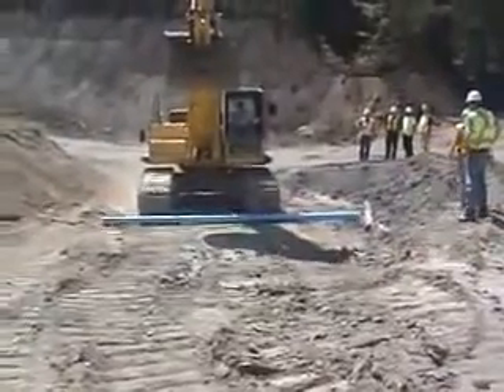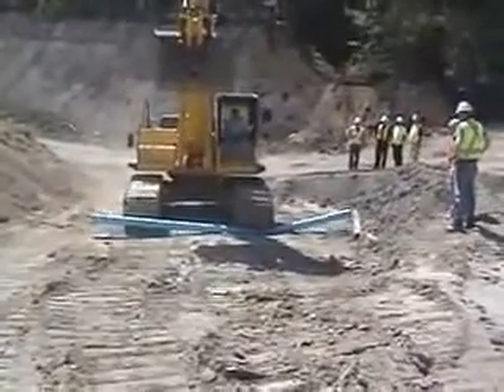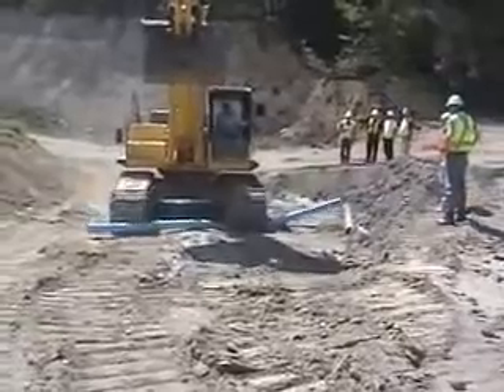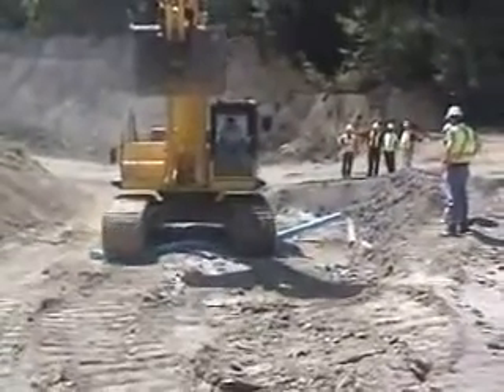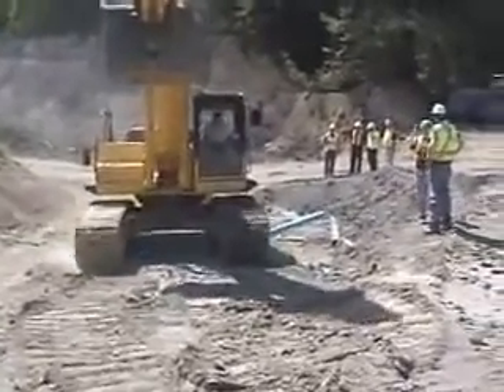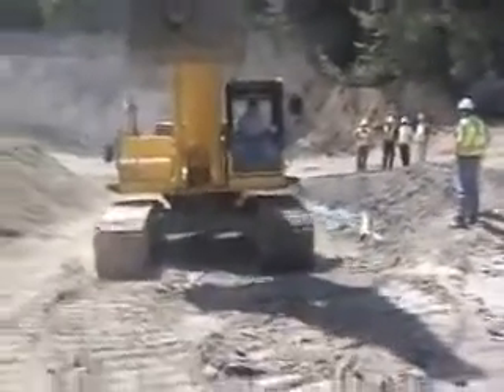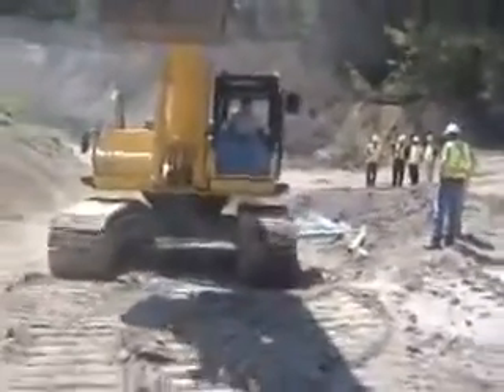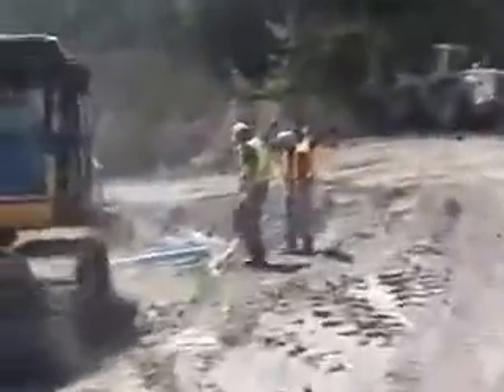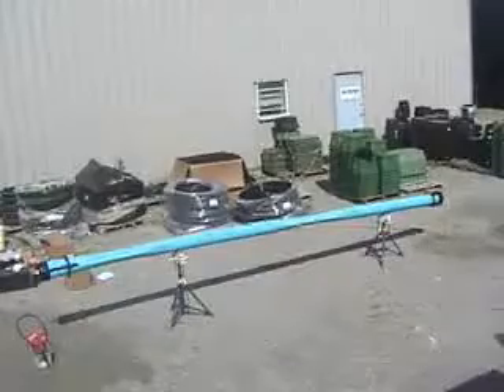Bionax was not only run over by the Kobelco 370, but the pipe was twisted when one track grabbed it prior to the other one. Even with this additional strain, no cracks were visible. However, there were obvious stress marks on the pipe.